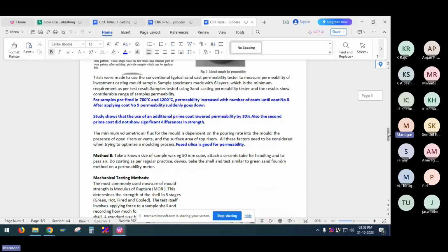So the pre-firing of the sample should be 700 to 1200 centigrade, and permeability is increased up to 8 coats. After that, it starts going down. So it is suggested to go for 8 coats in the normal shell production wherever possible, maybe for lesser weight castings. For heavy weight castings, normally people go for even 12, 14 also, to have a shell thickness.